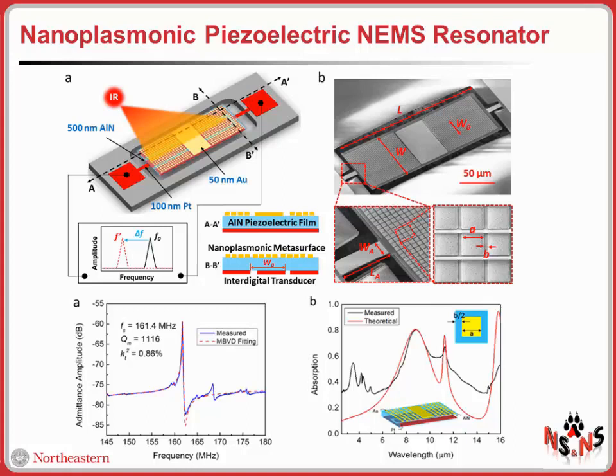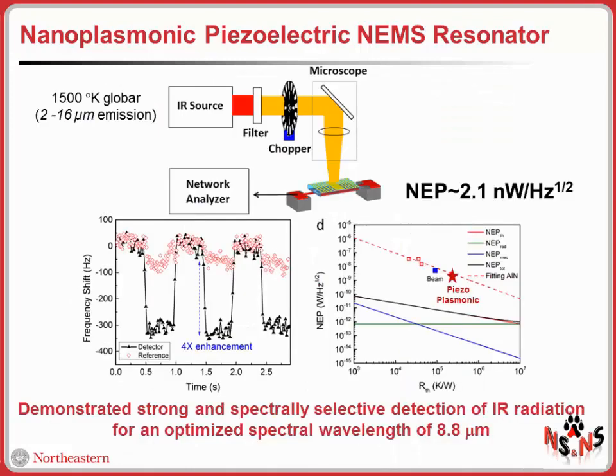But what is very interesting here is that if we measure the absorption spectrum of this nanomechanical resonator, now we have a very nice absorption band, which is about 80% absorption at the peak point, centered around 8.8 microns for this particular example. So now we tested this prototype. We exposed it to a 1500 Kelvin glow bar with an emission band between 2 and 16 microns. Despite this broad emission of the source compared to the relatively narrow absorption band of the device, we were still able to measure an improvement in responsivity compared to a conventional nanomechanical piezoelectric resonator, thanks to the improvement associated with these nano-plasmonic structures that we put there.